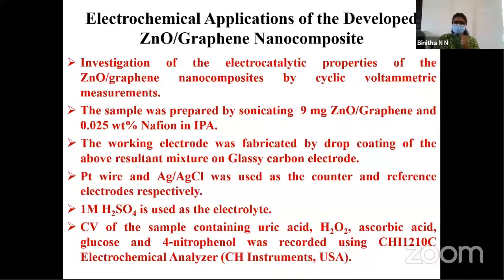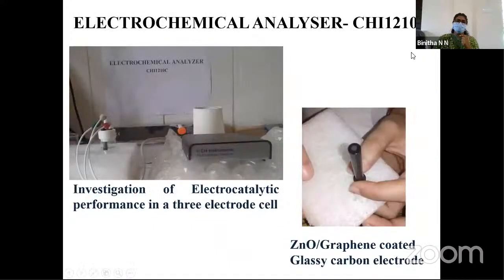We have sensed 4-nitrophenol in the presence of other interfering reagents such as uric acid, hydrogen peroxide, ascorbic acid, glucose, etc. Because sensing should always be selective. Otherwise, we cannot ensure that it is a single component. Or if the selectivity is very low, we cannot say it is 4-nitrophenol or uric acid or whatever it is. These are the photographs for the electrochemical sensing investigation using an electrochemical analyzer. The zinc oxide graphene is coated on a glassy carbon electrode for its sensing.